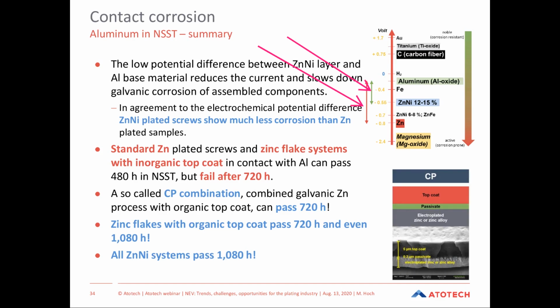Standard zinc plated screws and zinc flake systems with an inorganic top coat can pass 480 hours, but they already fail after 720 hours. A so-called CP combination, a combination of a galvanic zinc process with an organic top coat, can even pass 720 hours. Zinc flakes with organic top coat pass 720 and even 1080 hours. And by far the best is a zinc nickel system. All zinc nickel systems passed 1080 hours.